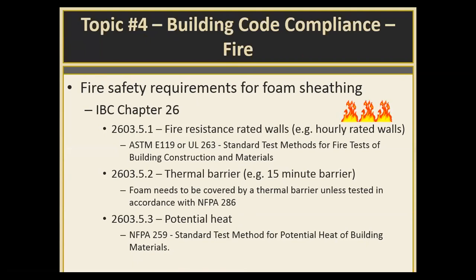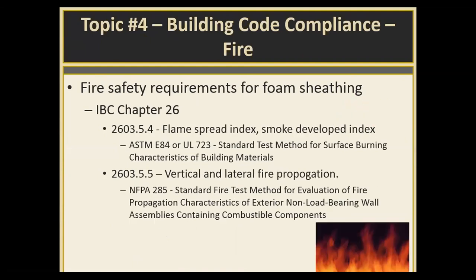Fire resistance rated walls or hourly rated walls are important and come into play when buildings are within certain proximity of one another. Thermal barrier requirements, we talked about earlier with exposed material to the inside of buildings. There are certain products that can meet NFPA 286, which is an exposed interior burn test. If they don't meet that test, then they need to be covered by a thermal barrier. There are potential heat requirements, which is often incorporated into the NFPA 285 requirement as well. But these two are the biggies that you see on a more common basis when it comes to fire.